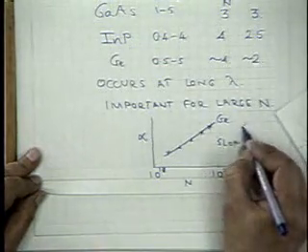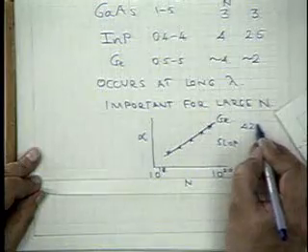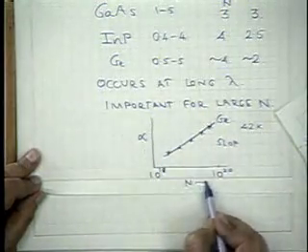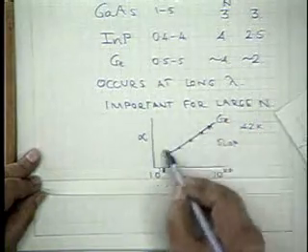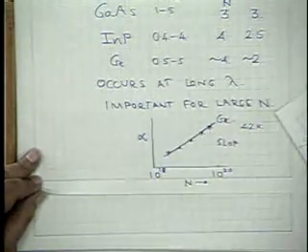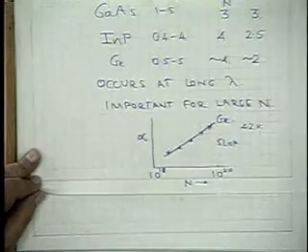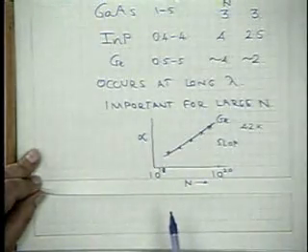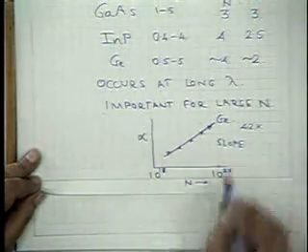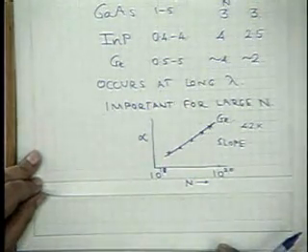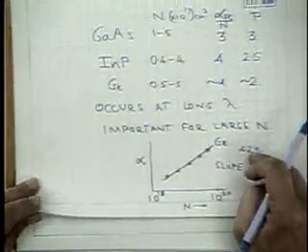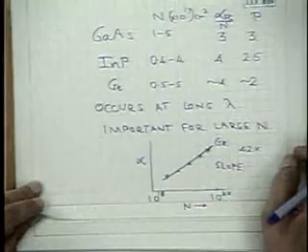At 4.2 K, it is found that alpha is roughly proportional to N. Similarly, one can plot alpha against lambda and find the exponent P. Now, I've just introduced the term optical phonons, acoustical phonons, etc.